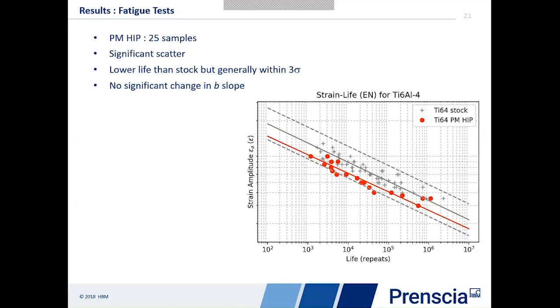Now this test considers powder metal hipped. So there are 25 samples here. The first thing we notice is there's more significant scatter. It's not bad. It's in the order of the wrought material, but there's a little bit more scatter than we found before. But still, the life is within that 3 sigma band. And in this case, there's no real significant change in the B slope either.